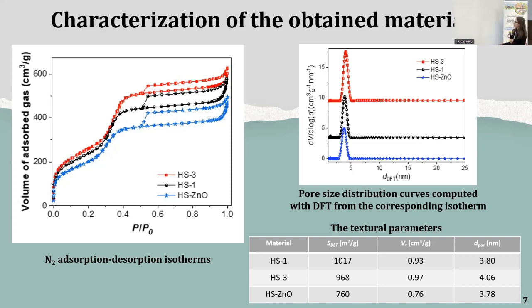And as you can see here, the presence of zinc oxide nanoparticles led to a decrease in average pore diameter, suggesting this way the presence of zinc oxide nanoparticles inside the pore mesochannels.